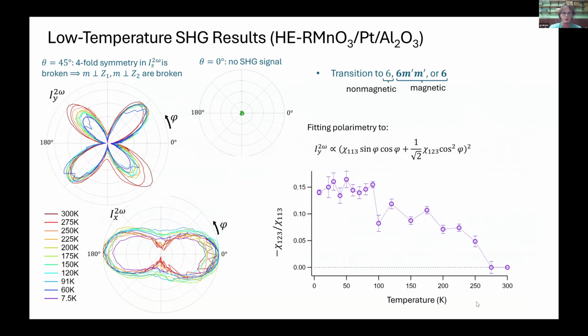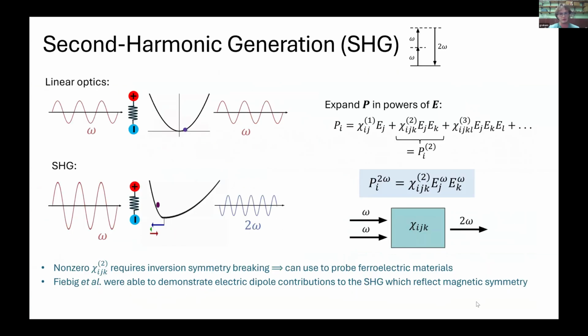So this is second order. Okay, so to clarify, magnetic SHG is coming from the second order. Yes, I know. But you can compute some linear response. How can you compare linear with the second order magnetic moments? In terms of linear magnetic effects, like getting a polarization, are you saying you would have a second rank tensor for the linear effect that depends on the magnetic symmetry?